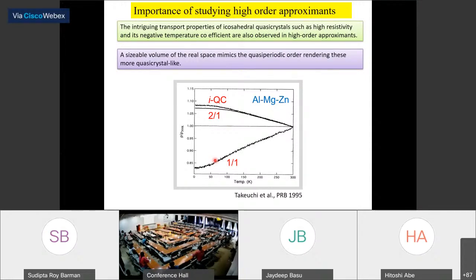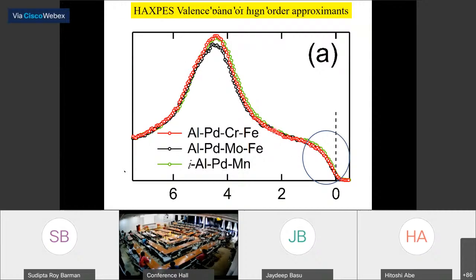So this is the importance of studying the high order approximants that we have. Their resistivity, which is similar to the quasicrystal, shows a negative TCR, the high order approximants, whereas the low order approximants behave like a metal. So this is the valence band of the high order approximants. And if you look at them, the AlPdCrFe, AlPdMn, well, they look not so different, but the devil lies in the details. And these are the details here.